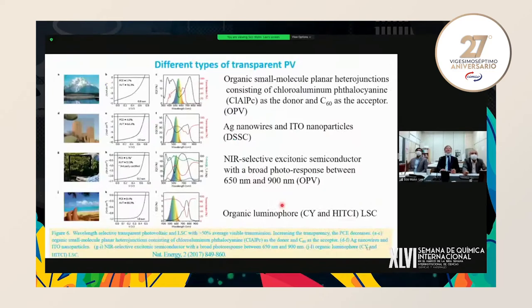Well, here are three different types of transparent photovoltaics. One typically is organic photovoltaic, and dye-sensitized solar cells are also available. Also, organic luminophores such as CY or HITCI LSC. When you look at the silver nanowire and ITO particle in DSSC, there is a PCE of 4.2, and the average visual light transmittance through this material is 64.4%. So if you have high PCE, high power conversion efficiency, you lose transmittance of visible light. So this is a typical case.